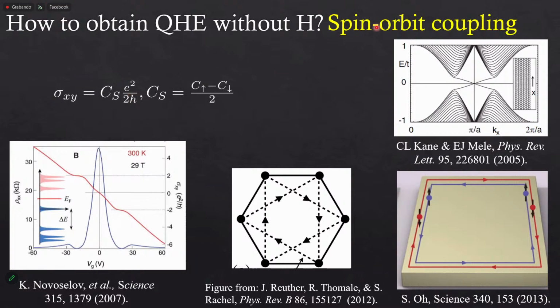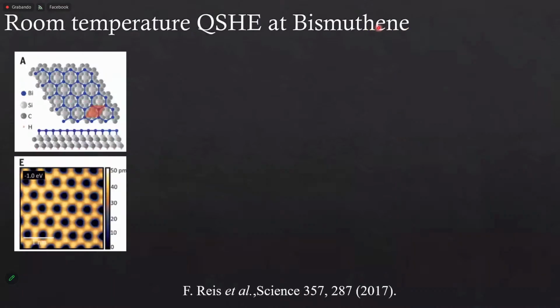So now it's nice because I know that there is some quantity here, spin-orbit coupling, that we can use to have these topological phases even without very high magnetic fields. So in principle, you should look for materials that have very high spin-orbit coupling to try to obtain this kind of interesting phase. A material that has it by itself is bismuth, because bismuth is a very heavy atom. So in principle, you expect to have a very high spin-orbit coupling.